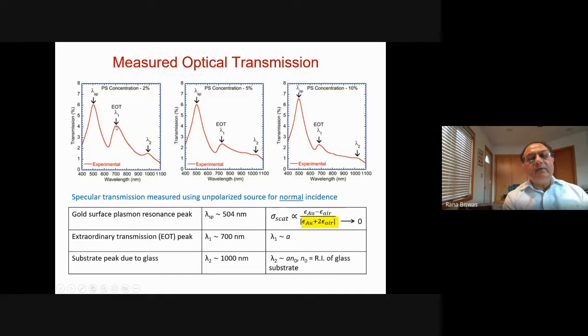The second feature is lambda 1, this extraordinary transmission peak. And it occurs at about 700 nanometers in all these three samples. So it's very close to the pitch of this structure. And the last feature is lambda 2, occurring at about 1000 nanometers, particularly for the first two films. And this is the refractive index of glass times the pitch. It's very close to that.